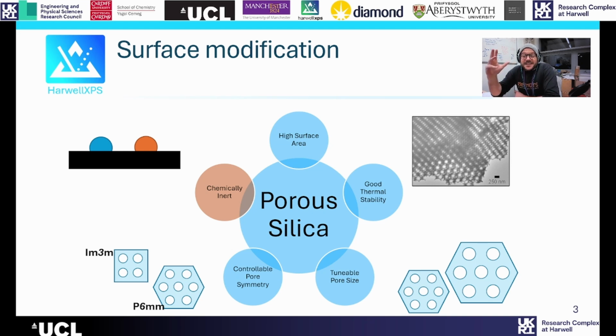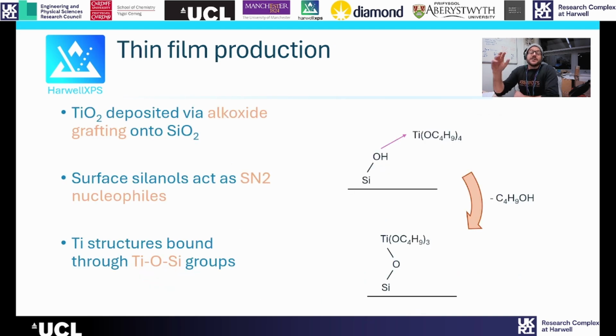To get them to do anything, you generally need to add some kind of chemical functionality, whether this is nanoparticles, surface coatings, tethered organic groups. Just something needs to be added to get them to do things. So that's what we've looked to do in this work, anchoring monolayer and sub-monolayer titanium coverages across a high surface area silica, known as SBA-15, in order to make them more chemically interesting.